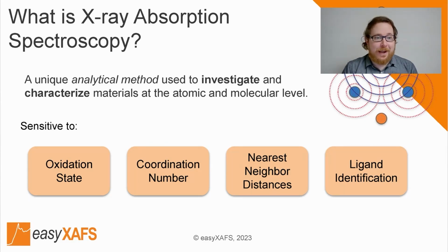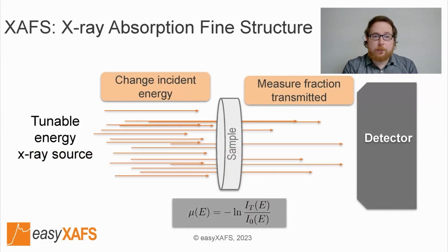Slightly longer answer, XAS is specifically the fine structure observed in the energy-dependent absorption of a material over regions near the binding energy of a core level electron. The most straightforward method of observing this is in a sample transmission geometry, as shown here on this slide. The logarithmic ratio between incident and transmitted intensity will tell you the amount of absorption that's happening in your material. Recording this over a range of incident X-ray energies together generates an XAS spectrum.